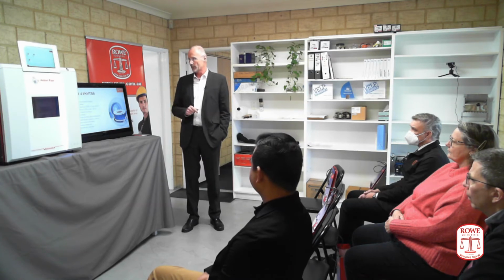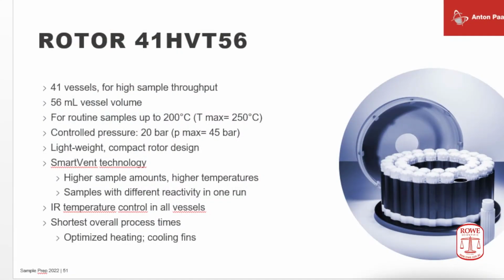First application examples I'm going to show you at the example of a 41 place rotor, which is used in high throughput laboratories. It is good for routine samples, easier to digest organic and inorganic materials that can be decomposed properly at temperatures of up to 200 degrees centigrade at a controlled reaction pressure of 20 bar. So this is the most important characteristics of a reaction vessel: temperature and subsequently pressure. 41 samples in one run.